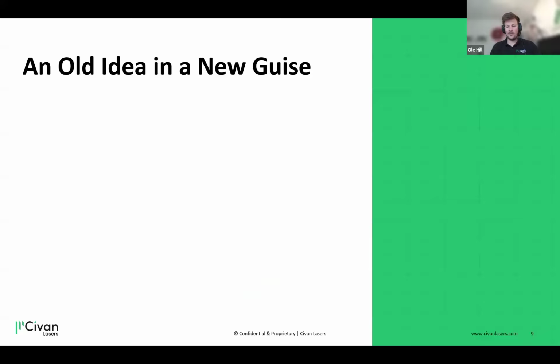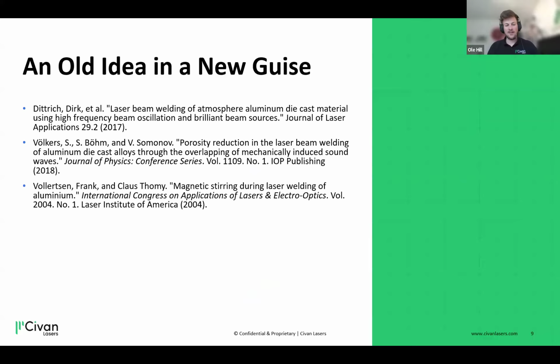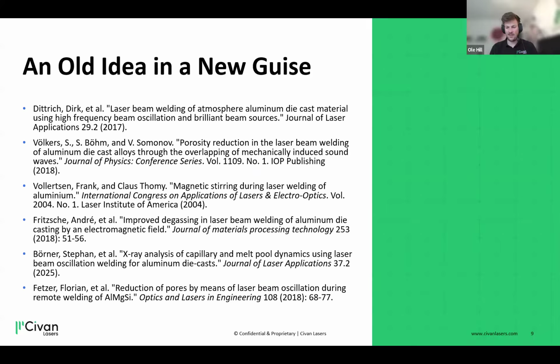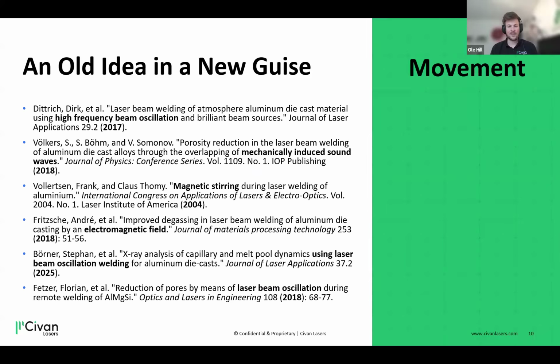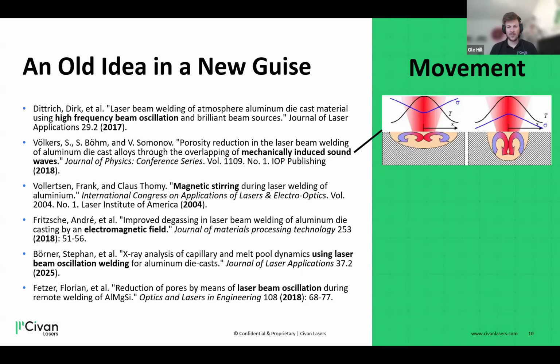Going back to what I presented in the first slides, the die-cast welding. When looking at the literature, we see the idea, it is just a broad overview for you, that something has to be moving inside the weld seam. So these are all publications on laser welding of aluminum die-cast, and they all have in common that the weld pool is moved in some way.